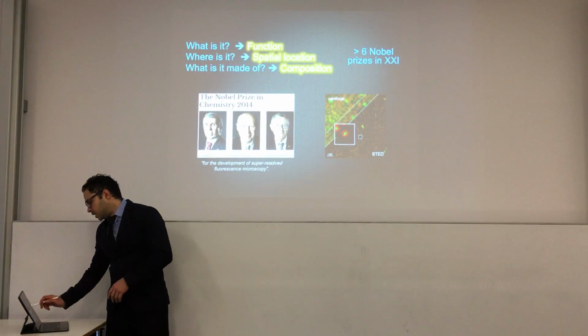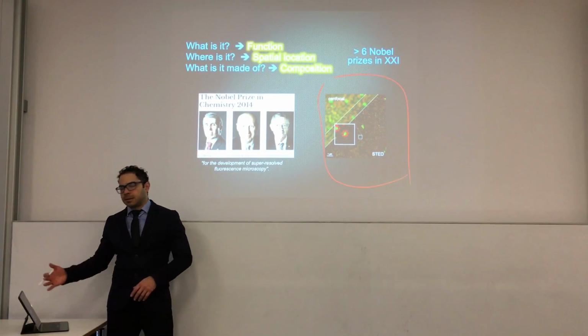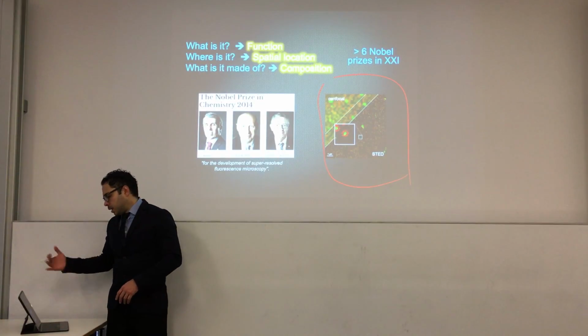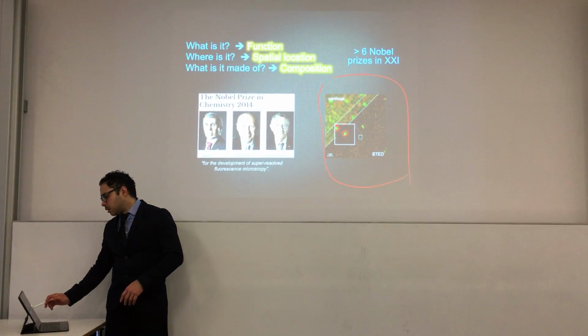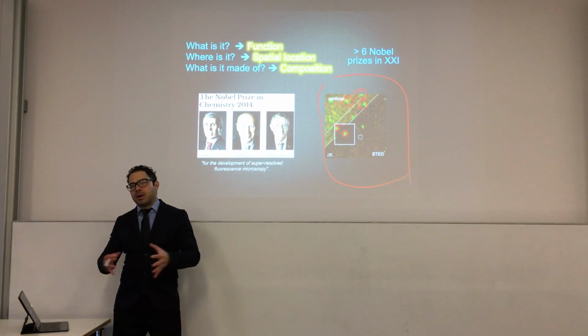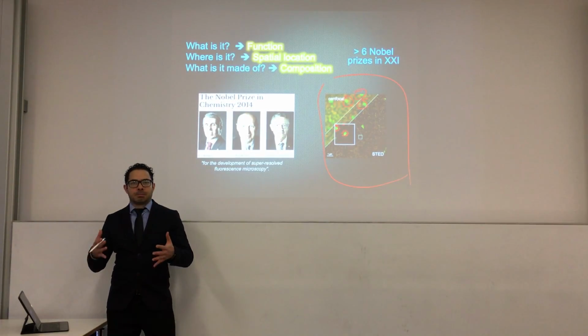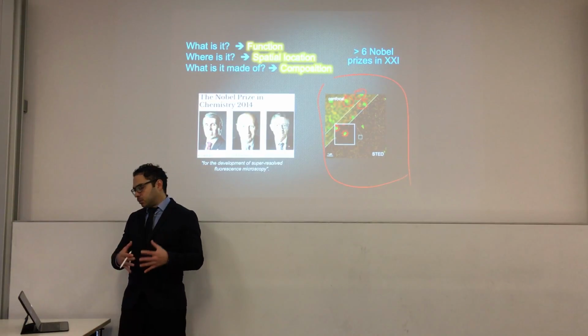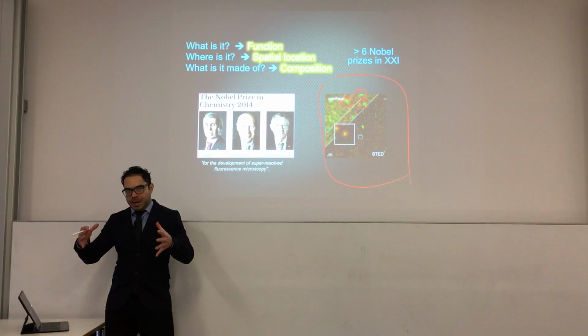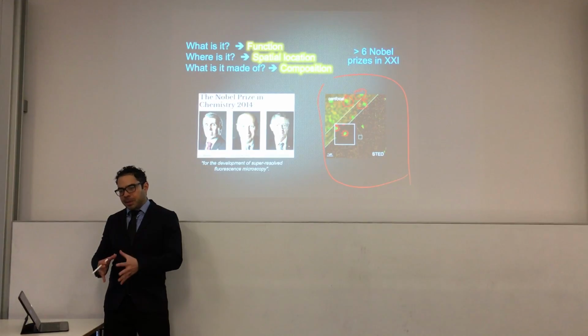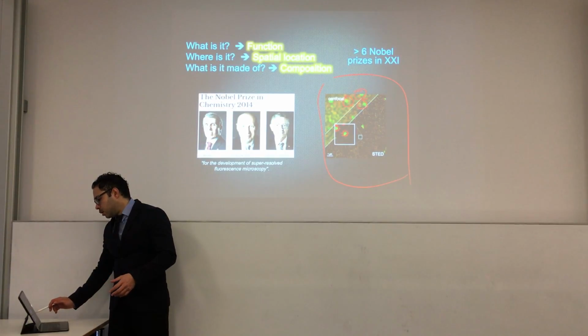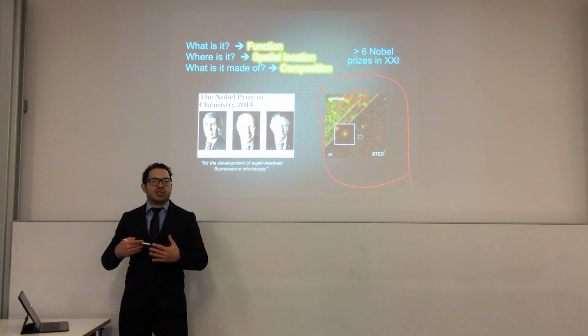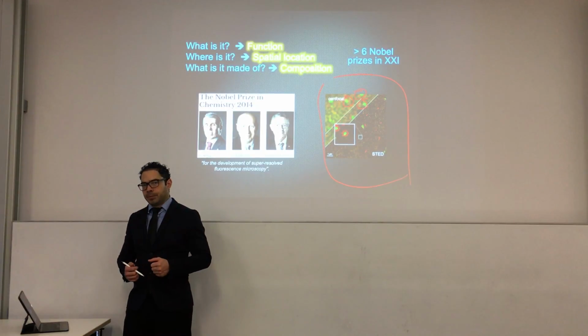This is illustrated by this image that we have there. It's exactly the same chromophores dispersed on a substrate, and you can see in the confocal image how large they look. It's because they are convoluted with the point spread function of your optical system, so you will see a very large agglomerate. While in reality, if you have a very good spatial resolution like STED, you can clearly see all these small points that you see in this image. If you zoom in, you can actually resolve and visualize a single chromophore.